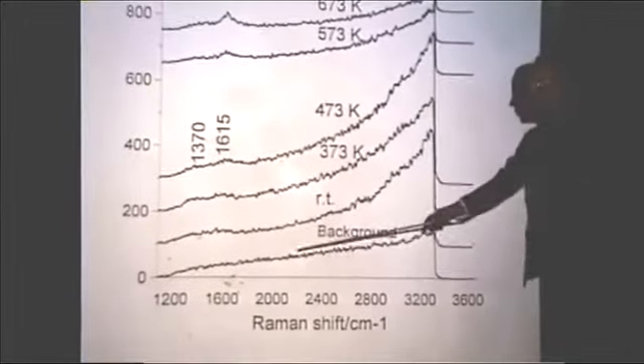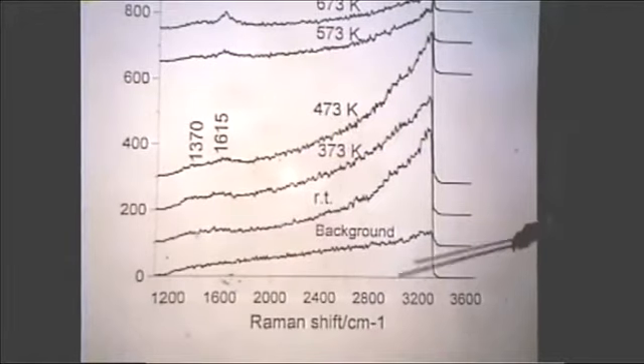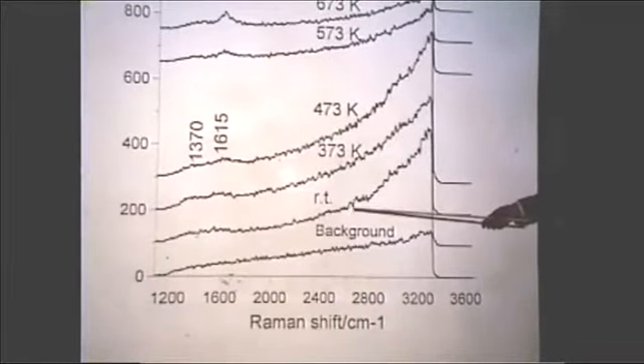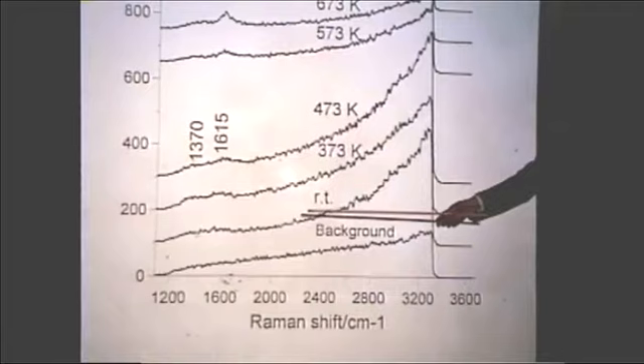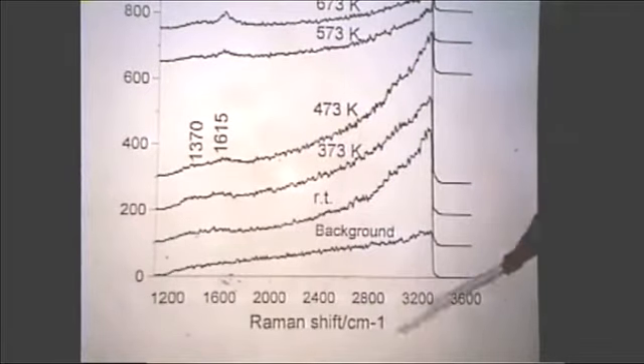Okay, so here's what you see before you do any propylene exposure. Here's the room temperature propylene exposure. We don't have these coke bands on this catalyst. So we don't have the room temperature polymerization that occurs on the acid catalyst, and that seems quite reasonable. We don't have acid catalyzed polymerization, so we don't have acid sites.